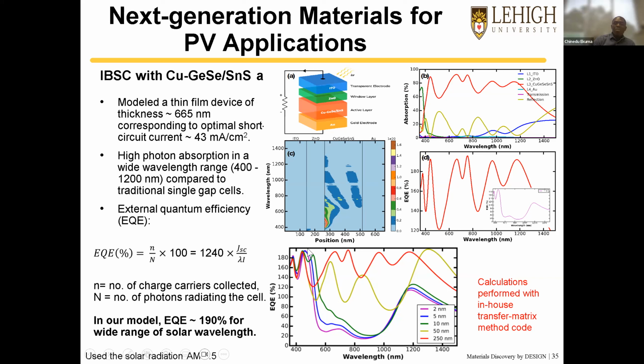But another important thing that we are showing is that at this important energy or frequency regime or wavelength regime, our active layer is independent of thickness. Remember, our active layer technically is at the extreme limit of a couple of nanometers or angstroms. So what we demonstrated here is that, even though it converges as a function of thickness, in these low energy or wavelength regimes where light absorption is highest, it generally does not depend much on thickness.